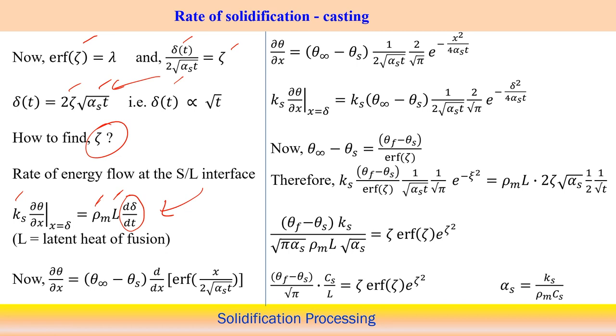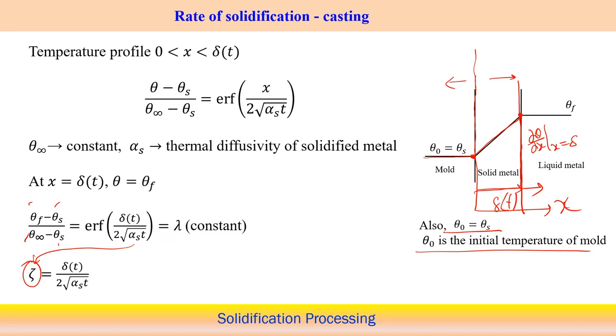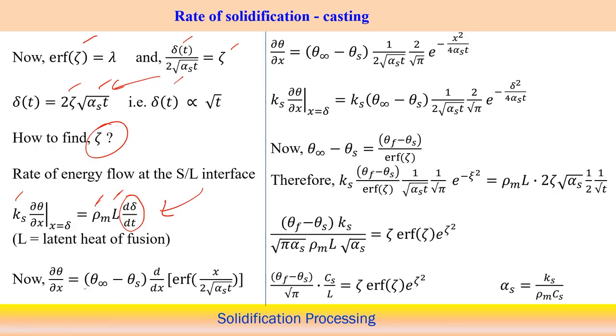Now, from our expression for the temperature distribution, which we have seen previously, we can find del theta by del x. So we need to calculate the value of del theta by del x from this particular equation: theta infinity minus theta s, d by dx of the error function of x by 2 root alpha s t. So here del theta by del x is this into d by dx of the error function, which we have already seen: 1 by 2 root alpha s t, into 2 by root pi, e to the power minus x squared by 4 alpha s t.